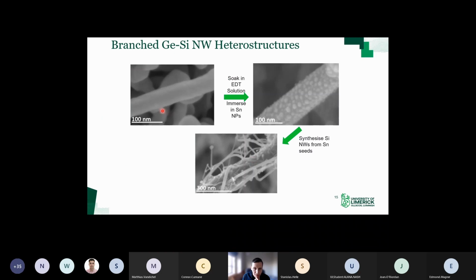So this is a look at that process on the SEM. You start with your bare nanowire, soak it in the EDT solution, immerse it in the tin nanoparticles, and then grow the silicon nanowires separately in the solvent vapor growth system. So you get this nice branched structure, and importantly, all the branches are well contacted to the stem.